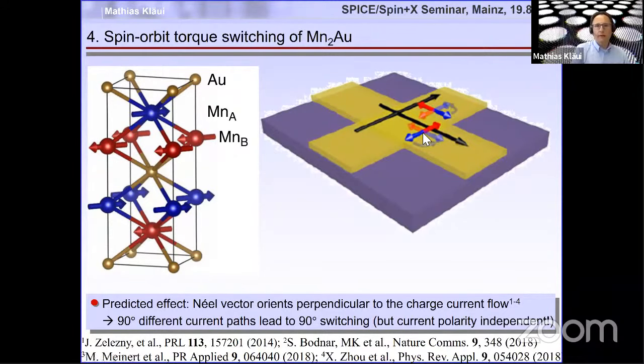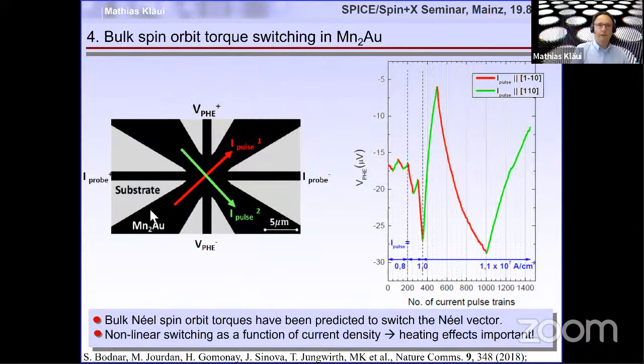And this actually works. So we did the experiment where we patterned such a cross made of manganese two gold. And then when we inject current pulses, say along this direction here, the 1-1-bar-0 direction, the AMR or planar Hall effect goes down. And if we inject current along the 1-1-0 direction, we actually get an increase in the planar Hall effect. So we can get switching up and down by 90 degrees of the Néel vector.